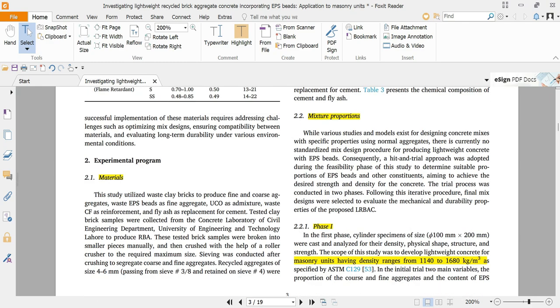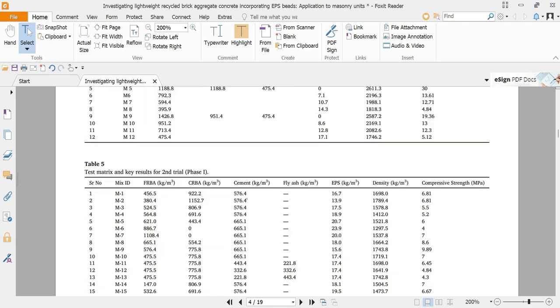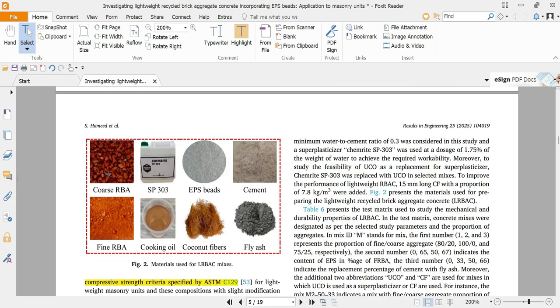So in this study, we produce the lightweight recycled aggregate concrete incorporating coarse recycled brick aggregate, fine recycled brick aggregate, EPS beads as a replacement of fine aggregate, coconut fibers to improve the tensile strength, cement as a binder, and fly ash as a partial replacement of cement. And we also used some superplasticizers to achieve the workability, and we also replace this admixture with the used cooking oil to improve the workability of the concrete and also to utilize this waste material.